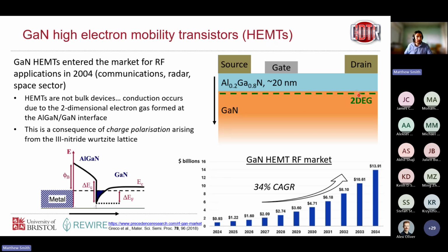It's called a 2-DEG. So unlike most devices where we have this bulk conduction where charge is moving all through the device, in this case the charge is localized very close to the surface in this 2-DEG layer. So this occurs due to a conduction band offset in the AlGaN and GaN, and also something called polarization or charge polarization at the interface gives us this effect. And it's a very positive effect because this thin sheet of charge is very mobile, so it acts as a channel for transistors. So we're passing current from source to drain, and we're controlling the flow of current using our gate electrode here. So with just a few volts on the gate, we can deplete the 2-DEG underneath in this region here and turn our transistor on and off.